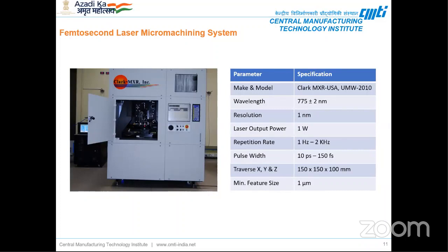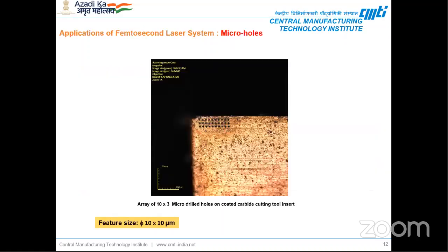The femtosecond laser system we have at CMTI is a Clark MXR make, having a wavelength of 775 nanometers and a stage resolution of around 1 nanometer. It has a laser output power of 1 watt and a repetition rate of 1 hertz to 2 kilohertz. It has a pulse width of 10 picoseconds to 150 femtoseconds, and the traverse is around 150 by 150 by 100. The minimum feature we can machine with this system is around 1 micron. So coming to the applications of femtosecond lasers.